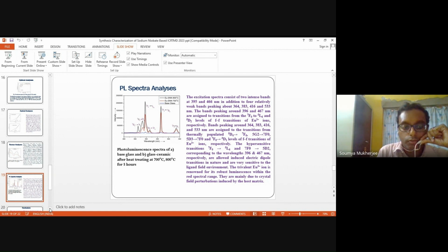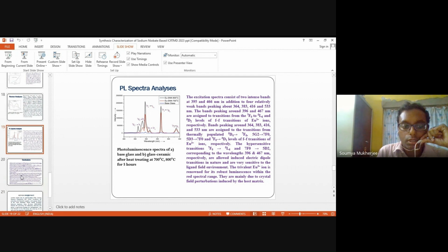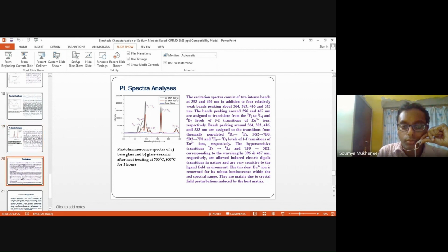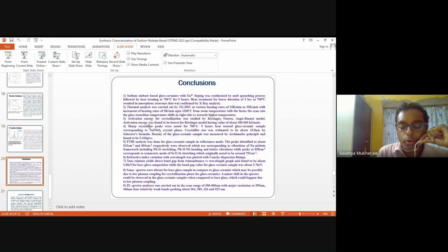So in conclusion, we can say that the process that we have followed is successful in creating this glass ceramic. The glass ceramic development is a very common solid-state melt quenching process, just a high temperature process, and we have carried it out successfully. Sharp crystalline peaks were noted only at 700 degrees Celsius for 5 hours of heat treatment, not at 3 hours, where there is still an amorphous peak, while the density has been calculated with the help of the Archimedes principle, which is around 3.4.